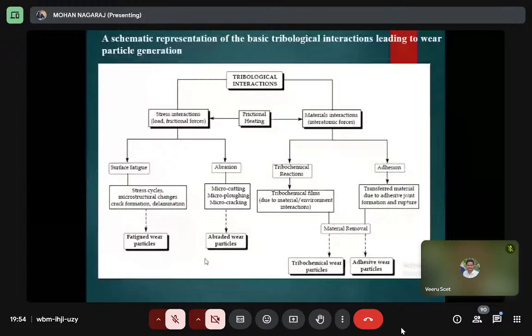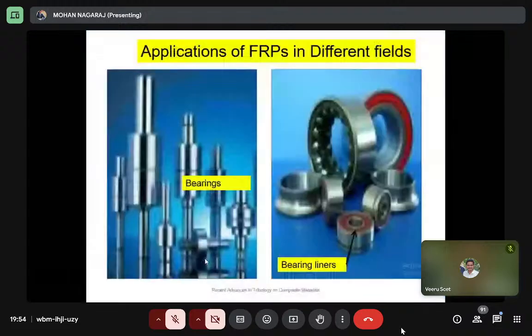Abrasion is micro cutting, micro plowing, and micro cracking in the materials, producing abraded wear particles. And in the materials, interactions are tribochemical, due to adhesive joint formation and rupture, producing adhesive wear particles. This is the general application of fiber reinforced plastics in different fields. Bearing liners: polytetrafluoroethylene materials are used for bearing liners. Generally, instead of oil or grease, self lubrication takes place. This is generally made from composite materials.